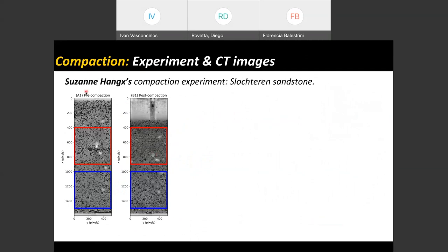On the left, you see the picture of the sample before compaction. On the right, you see it post-compaction. In fact, you can see the piston here, the metal piston that compacted the sample. Right away, you can see that the porous structures have changed because the material has compacted. Now, the images are one-to-one, so this is about half a millimeter across, and this is about 1.5 millimeters vertically.